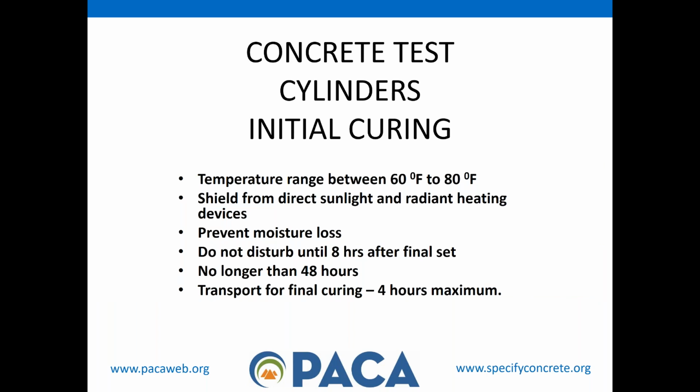To review real quick what we need these cylinders to be kept at. All cylinders on a job site between 60 and 80 degrees, prevent moisture loss, not disturbed until 8 hours after final set, and they can only remain on a job site for 48 hours until they're transported to the lab for final curing. That's all cylinders.